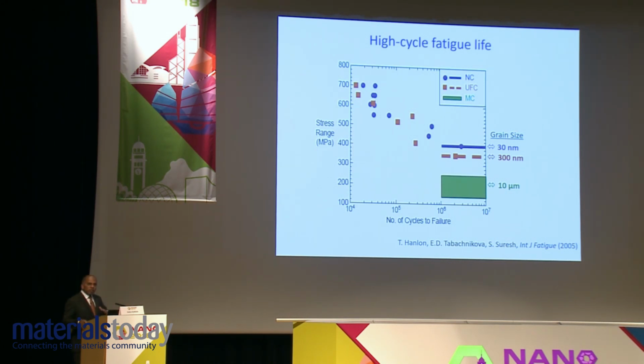When you go from microcrystalline to ultra-fine grain material, when say the grain size decreases to about 300 nanometers, your endurance limit increases by more than 50%. If you now go from ultra-fine grain to nano-grain material, where the grain size is of the order of 30 nanometers, this is electrodeposited nickel, and what you find is that the endurance limit still increases. So in high cycle fatigue, which primarily captures the life to initiate fatigue cracks, you get a beneficial effect of the high strength because of grain refinement in a nanocrystalline material.